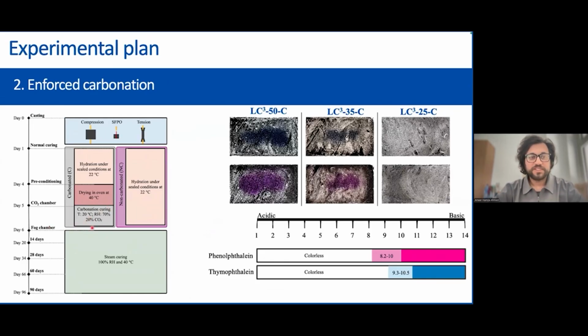day. Once this was done, we took all the samples, whether the carbonated set or the non-carbonated set, and we put them in the fog chamber for an additional 14, 28, 60, and 90 days. The conditions in the fog chamber were 100% humidity and 40 degrees centigrade temperature, because we wanted to see the effect of this accelerated hydration afterwards. So if there is degradation, we can notice it better. And after these curing times were concluded, we took out the samples, and for the carbonated ones, again, we cut the specimens and did the phenolphthalein and thymolphthalein indicator test again, and here you see the results.